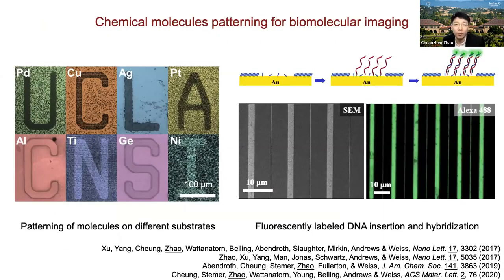Using similar approaches, we were able to pattern molecules on different metals and semiconductors using CLL. On the left are scanning electron microscope images of the patterned molecules on different metals and semiconductors with false color, including copper, silver, platinum, titanium, and germanium, as we expanded beyond the gold surface. One application of those patterned molecules is for biomolecular imaging. Here in the red, after the CLL, we can backfill with single-stranded DNA into those lifted-off areas. Then we can have hybridization with another fluorophore-labeled DNA for biomolecular patterning. In this case, the left one is the SEM image of the patterned molecule, and this is a fluorescence image of the backfilled DNA molecule.